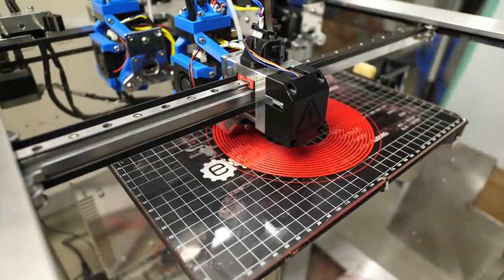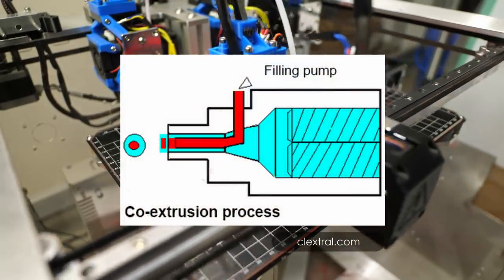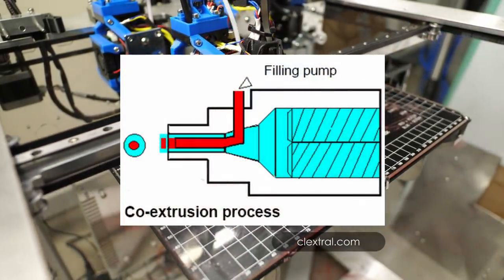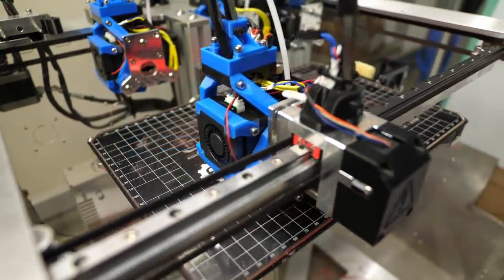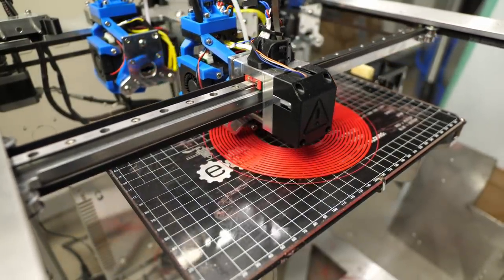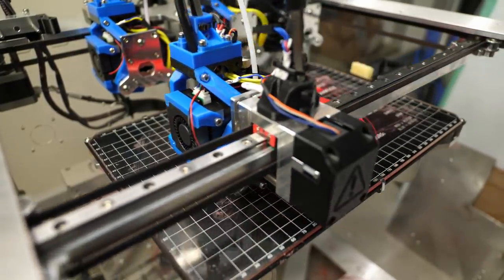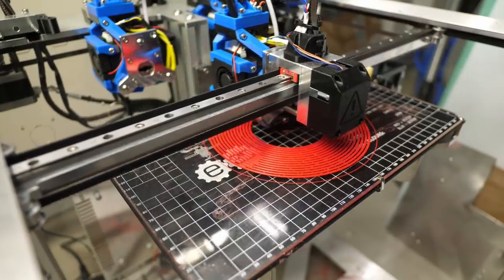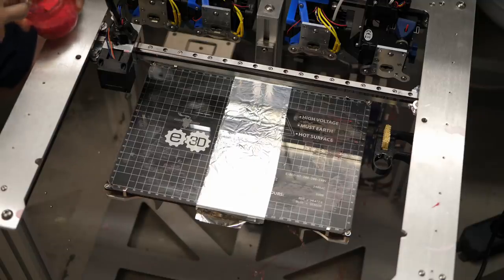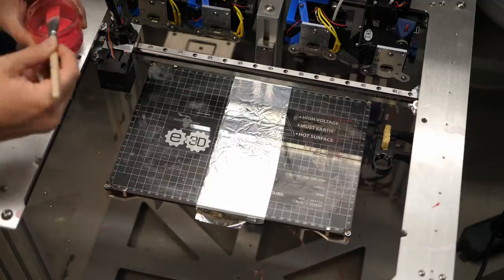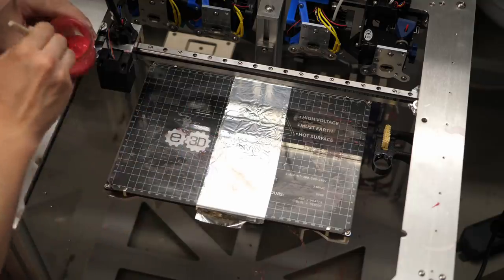Just on a side note, if you wanted to make such a multi-material filament on an industrial scale, there are co-extrusion machines that can directly extrude those types of filaments, though they are more expensive and more complex than a normal single screw extruder. Printing wasn't without problems because at first I had to make sure that the material sticks to the print plate. Usually I would have used typical adhesion sprays and liquids, but since they always leave residues on the parts, this wasn't an option for the filament because that could later contaminate and therefore ruin the filament. So I remembered a trick from the old days and mixed myself some ABS slurry by dissolving ABS and acetone that can be brushed on the glass bed and only leaves a thin film of material on it.